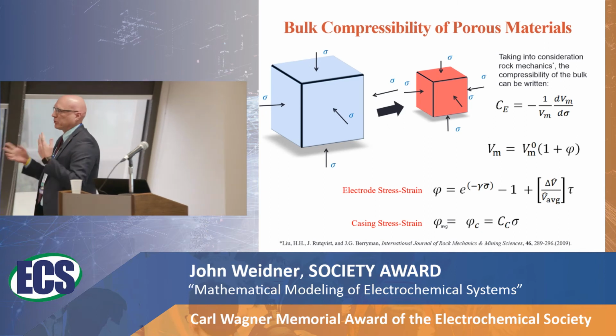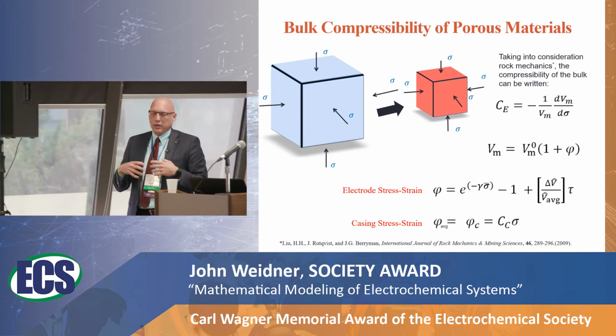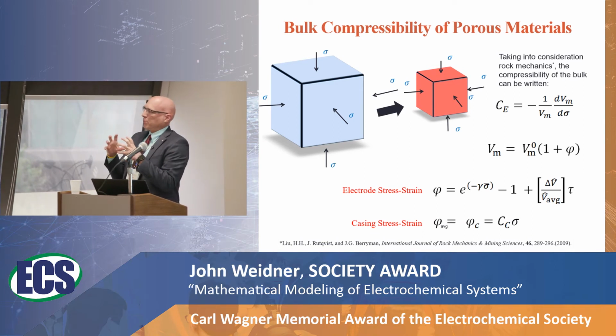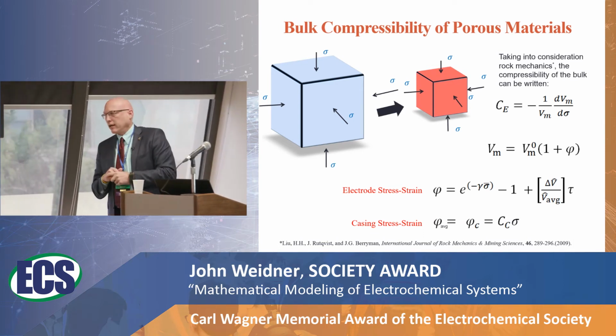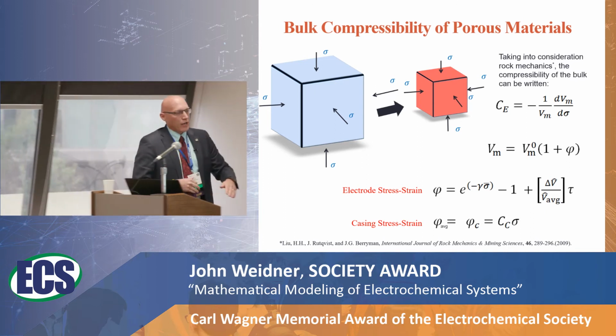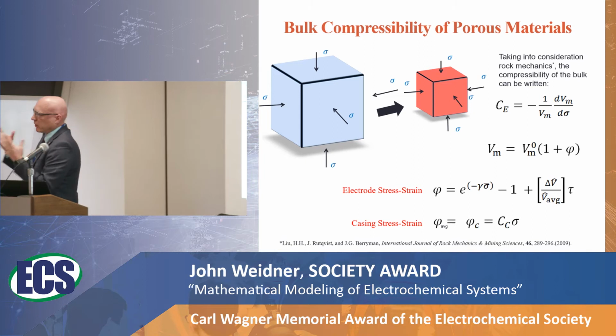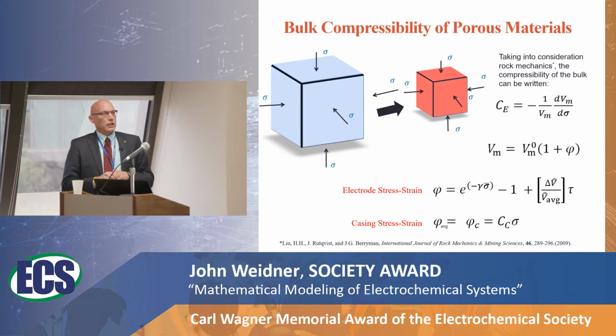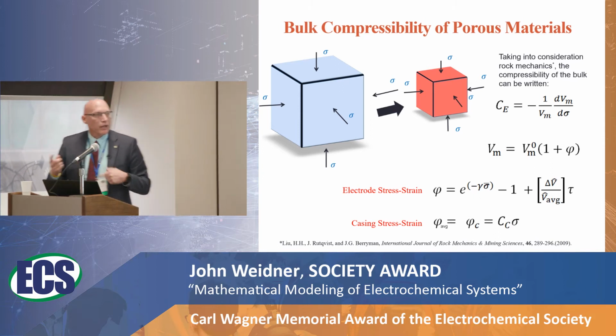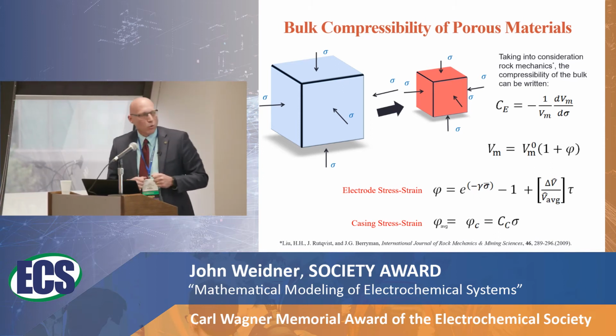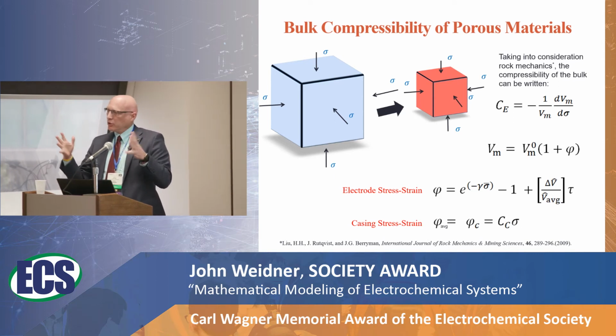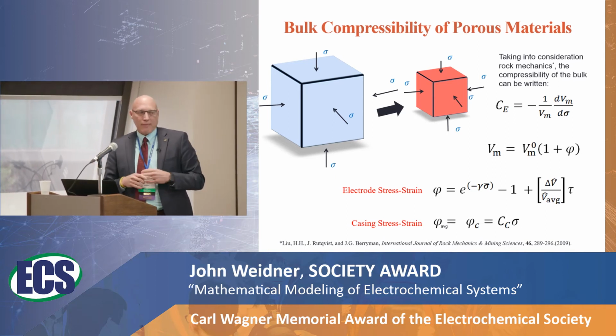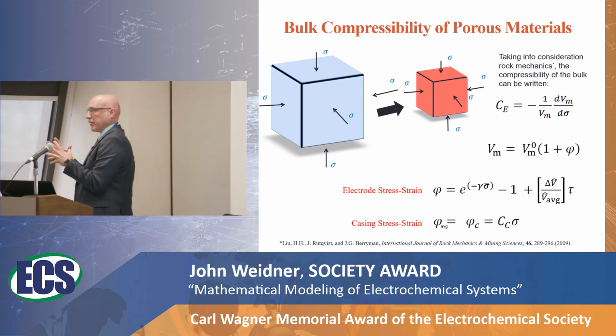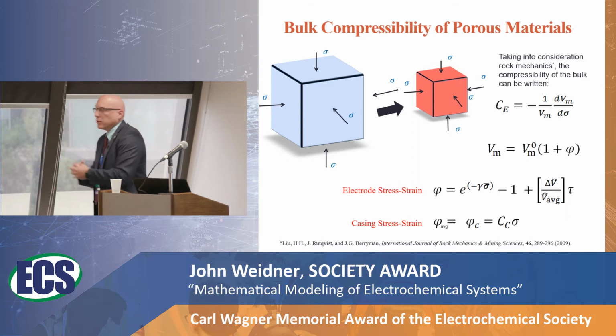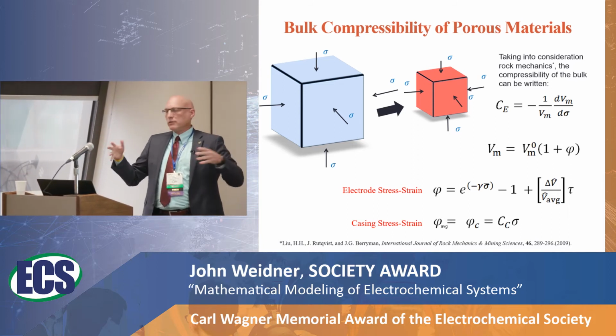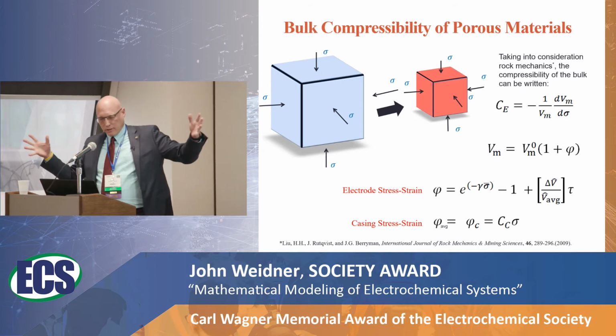is a logarithmic relationship between your stress-strain curve. It's basically saying that if the rocks, in their case, if the compressibility of the rock is constant, you should get an exponential relationship between stress and strain, and you balance that between what's holding it back. So in our case, the can that all the active material sits inside. And so now we have an additional relationship that tells us what does the volume change do and how does stresses that build up inside that. And that's got to be balanced then by the can. So if the can is rigid, it can't move, everything's going to go into porosity change. If the can, like a pouch cell, doesn't offer any resistance, then the material will expand.